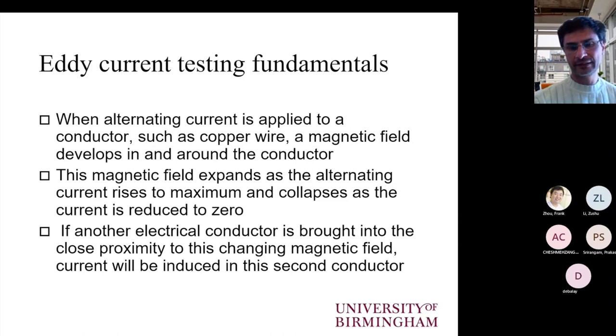And when this electromagnetic field is changing, it will result in eddy currents induced in a conductor when we bring this electromagnetic field close to it. If there is no defect, these eddy currents will just flow in a regular pattern depending on the coil shape that we have used, and they will generate a secondary field which will remain undisturbed. However, if we have a defect, these eddy currents will be disrupted, their shape will be disrupted, and of course that will change the secondary electromagnetic field, which will give us changes in the impedance of the coil, and that will be the signal that we detect from the presence of a defect.